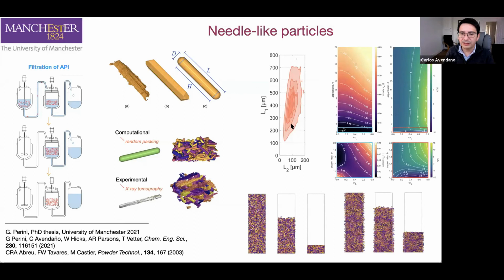is the distribution along the L1 direction, along the Y direction in this diagram. The higher that coefficient is, the broader the distribution of lengths in the particles you have; the lower it is, the more centered they will be around the mean. And in the Y-axis, what we have is the average aspect ratio of that distribution. So the center of that distribution is this aspect ratio here. For example, for this particular system, the average will be at 400 micrometers in length with about 100 micrometers in width. So that will give you an average aspect ratio of 4.